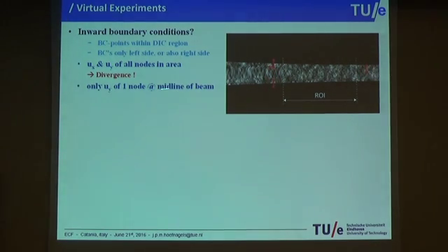So the next thing is, okay, let's more resemble the virtual experiment just by one point here, and still divergence here. Now we realize we're not exactly describing the same boundary conditions anymore, because normally in the virtual test, if you apply a displacement here, that would give a different moment than if you apply it here. So we said, let's have 2 of them, so we apply basically an angle at these 2 points. Well, now we're getting closer, 50% error.